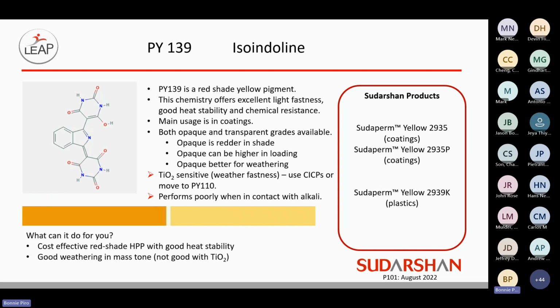Pigment Yellow 139, isoindoline, is a very red shade pigment. It's sort of an overall pigment primarily used in coatings. However, you can get a transparent version as well if required. The opaque version is going to always be redder in shade and is better for weathering and can be higher in loading, primarily because the particle size is going to be bigger.